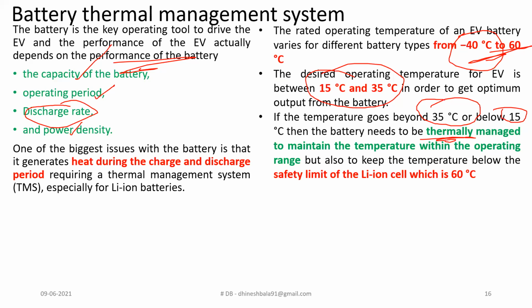So the battery needs to be thermally managed to maintain the temperature within the operating range, but also keep the temperature below the safety limit of the lithium-ion battery cell, that is 60 degrees. So it should never exceed 60 degrees. Once it exceeds 60 degrees, the alarming of battery degradation would start to a greater level.